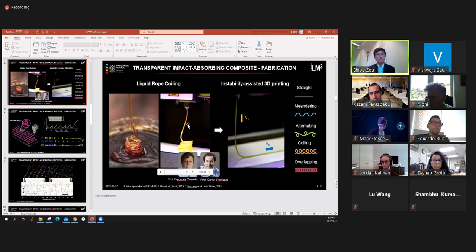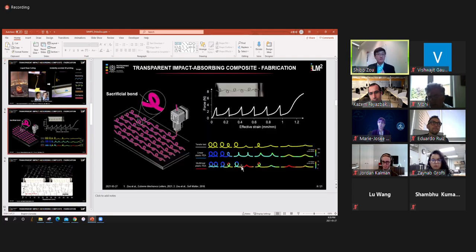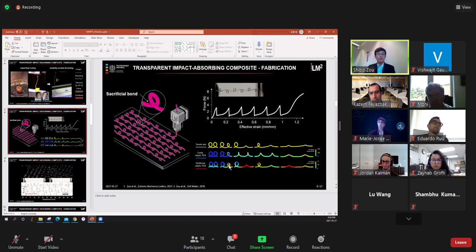And also we tried short fiber reinforced 3D printing filaments, those commercial ones, carbon fiber reinforced thermoplastic filaments. For normal FDM 3D printing of those short fiber reinforced thermoplastics, you can increase the stiffness, of course, and the strength of the material. But in our case, we need a large scale deformation of the fiber during the unfolding process. So if we use the short fiber reinforced 3D printing filaments, there will be no problem creating this structure. But when we do the mechanical test, because it's very rigid, it's also very brittle, especially in terms of bending. So it just breaks prematurely. So that's why we chose polycarbonate here. Yeah. Thank you. It was great.